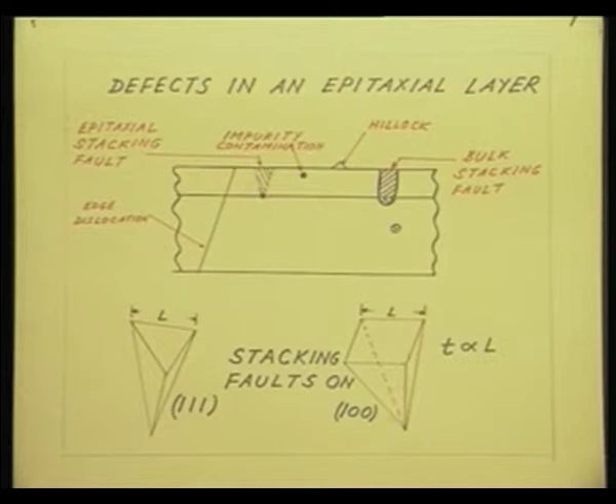Now, here I have a schematic representation of some of the defects in the epitaxial region. First of all, let us look at this line. By this line I want to represent an edge dislocation. You know, an edge dislocation is an extra half plane of atoms which can be viewed in 2 dimensions as an extra line. So, if this edge dislocation is present in the bulk crystal, as the epitaxial layer grows, this dislocation will simply carry on into the epitaxial region also. It will extend all the way into the epitaxial region.